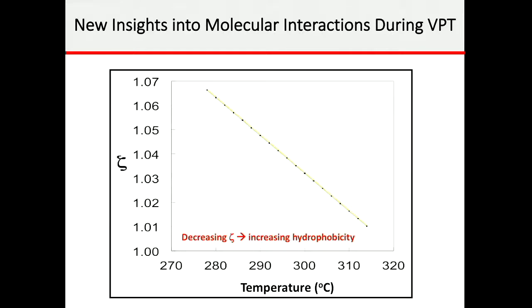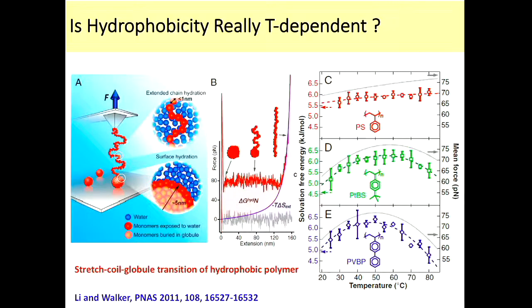This was an observation that we made while doing our theory, by the way. There was no experimental evidence on that. But interestingly, this experimental evidence came in a PNAS paper by Li and Walker later. As you can see, this is a coil-globule transition of polystyrene from a globule state, and you are stretching the polystyrene molecule, and you are measuring the force. And as you can see, as the temperature increases, the force starts increasing. So this was the first indication that what we had deduced in 1995 was right. And there are some other evidences also.